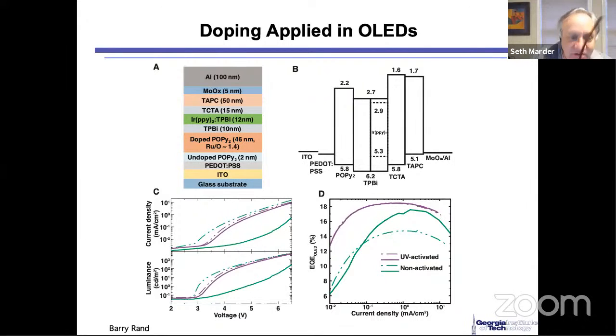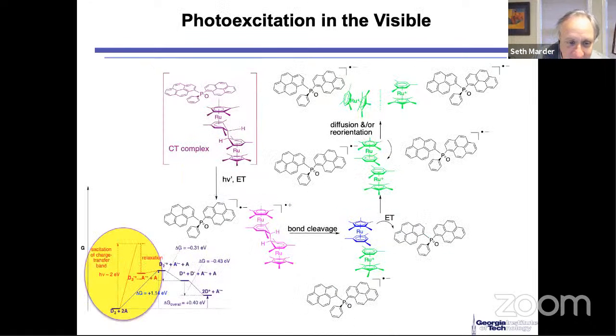And that once you start cycling it, you generate light that activates the dopant, and then eventually the system's doped. Well, that's all well and good, except for one thing. Every one of the materials that we put into this system only absorbs in the ultraviolet, and we're making a green dopant.